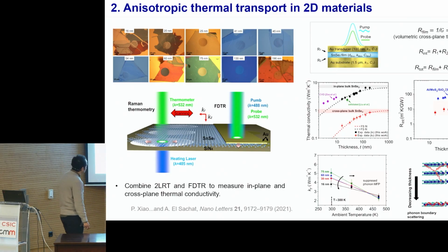And here you see, by performing these measurements, we can extract the thermal anisotropy. So we can say how much heat flux propagates in-plane and cross-plane in our membranes, in our 2D materials. And one interesting thing here is that the in-plane thermal conductivity is changing with the temperature. So we saw that actually the membrane thickness doesn't matter anymore if we go to very high temperatures, since the phonon-phonon scattering becomes dominant.